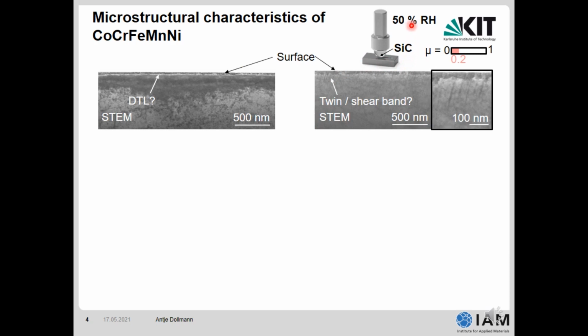Here you can see my first tribological system. So here is the cobalt chromium iron manganese nickel alloy. We have a silicon carbide sphere as counterbody in humid air. And we have again a normal load of 2 Newton and a sliding velocity of 0.5 millimeter per second. This system resulted in a friction coefficient of 0.2.